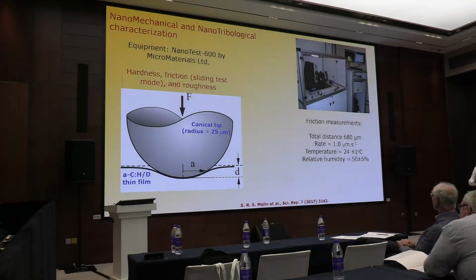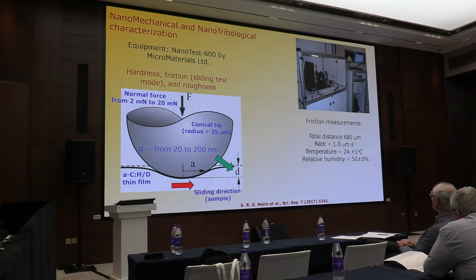Well, we characterized, but not by AFM, by nanomechanical nanotribometer. We use a conical tip and slide on the thin film samples of carbon with different content of deuterium and hydrogen. This is the photo of the equipment. I will check the time. It's okay.